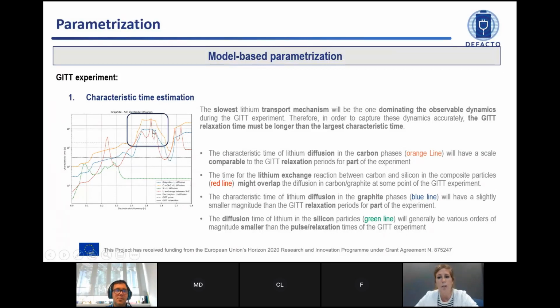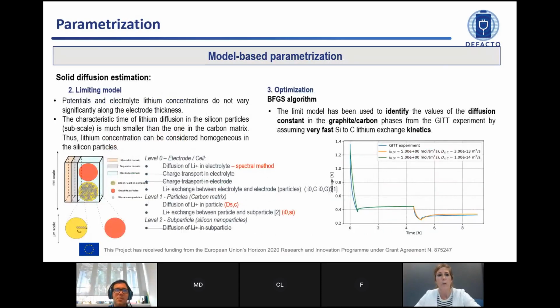And then we have this blue line, which is related to the diffusion in the graphite, and it's a little bit under the relaxation time, so it will be faster, and we won't be able to see it. And then we have the diffusion in the silicon, which is much faster. When we say it's really fast, there are no concentration gradients in the silicon, so we can avoid it, or we can skip it. So considering this, we have built these limiting models.